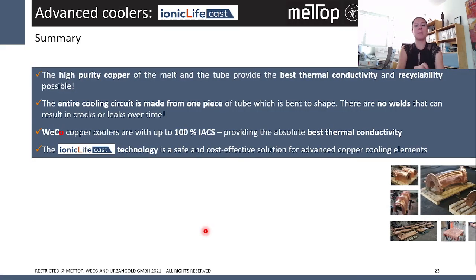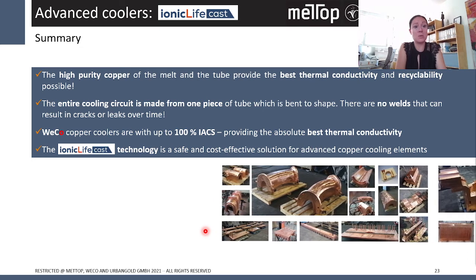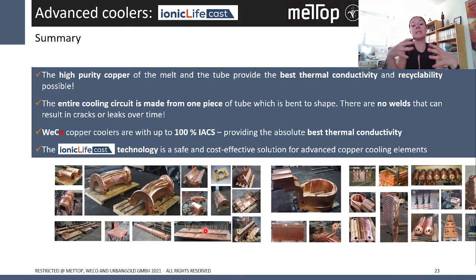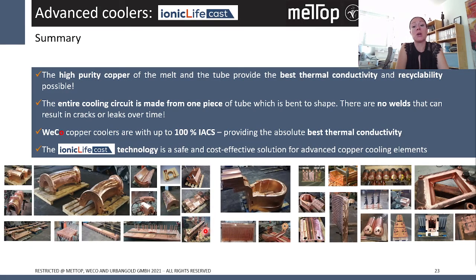Just to keep the good things in mind, let's sum up what's so special about our IonicLife cast technology. It is high purity copper cast directly on copper tubes. So you have a perfect bonding, which provides best thermal conductivity. Also, since it's just copper in copper, it provides perfect recyclability. You can directly remelt it and gain the full copper value. The entire cooling circuit is made from one piece, so there are no welds, which is also very good because welds are always a weak spot in every cooling loop. You think of Monel pipes, it's always the welds, but this is just a bent copper pipe without any welds.